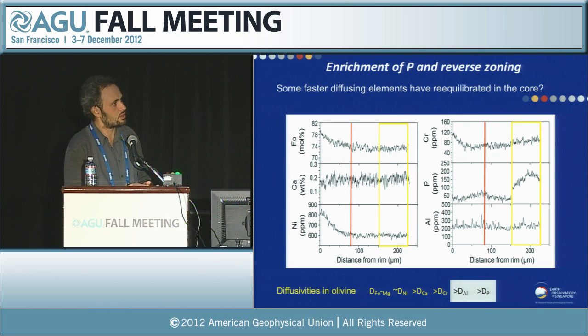And the second one is also this part. You see that the crystal is reversely zoned, so forsterite going towards the rim. This is showing this replenishment event, more mafic magma coming in. You see it also in the nickel. Chromium is more complicated. You have some down and then up. Apparently this correlates with some high phosphorus here, which we'll not look at in detail, but it's also happening.